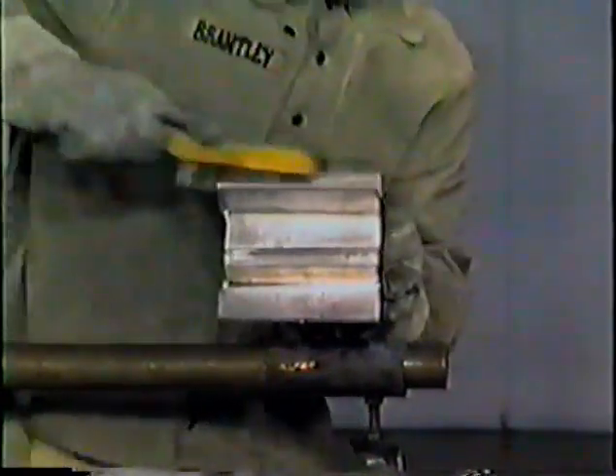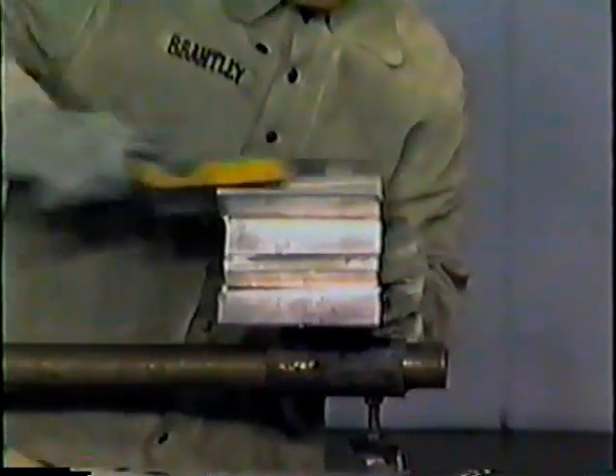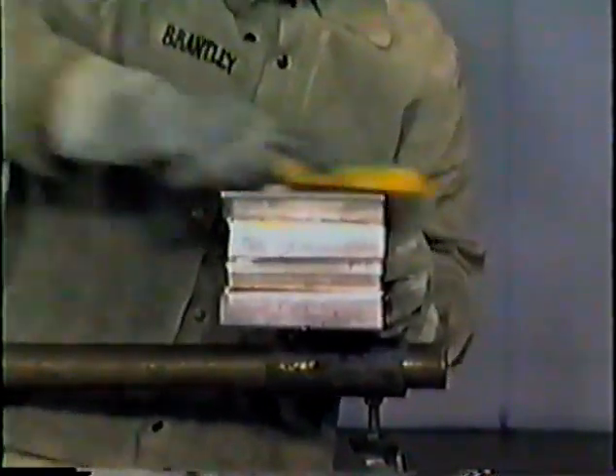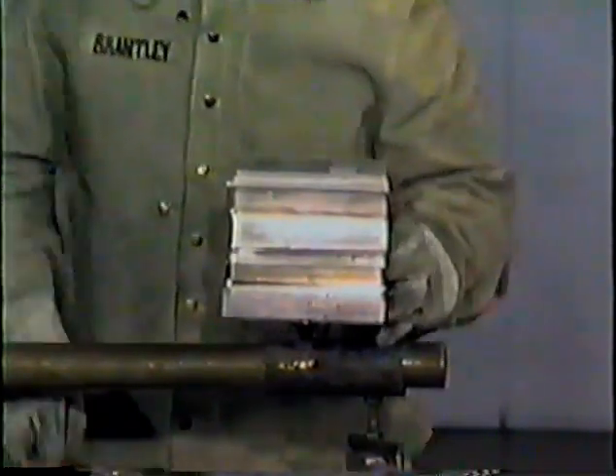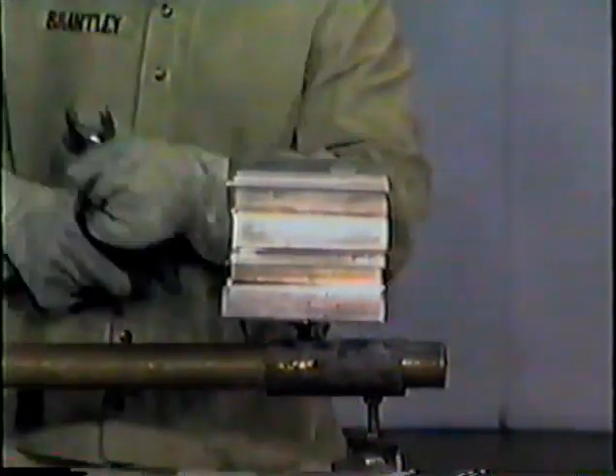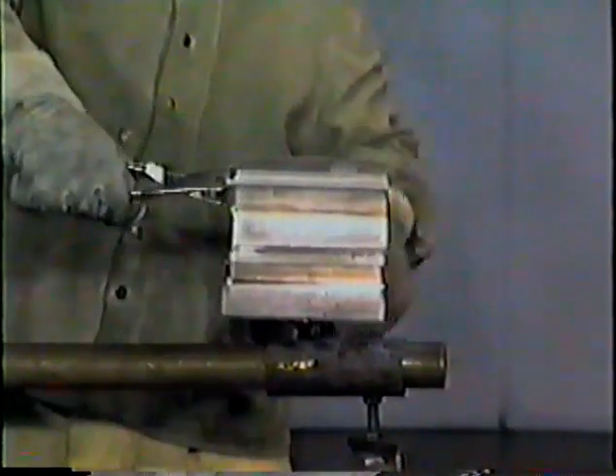The forehand technique is preferred for aluminum, as it provides a cleaning action ahead of the molten weld metal, which promotes wetting and reduces base metal oxidation. However, the drag method may be used depending on immediate circumstances. Wire brush your bead. The bead should look like this.